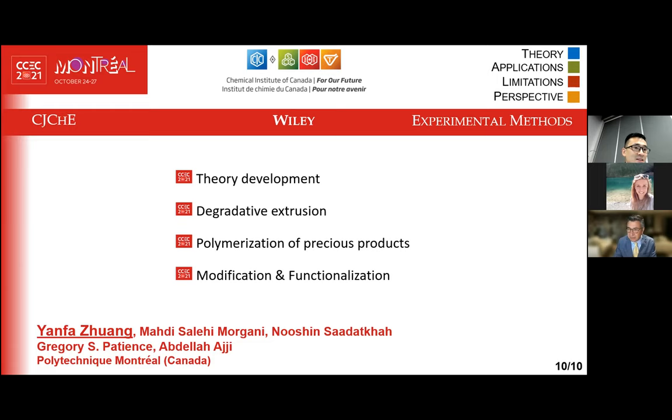Yes. Normally after the extrusion, the molecular weight of the polymers will degrade, but in reactive extrusion, you can add some chemicals inside to increase the molecular weight of the polymer. And there are two types of recycling methods using reactive extrusion. One is the reduction of the molecular weight. And another one, you can increase the molecular weight of the polymer.